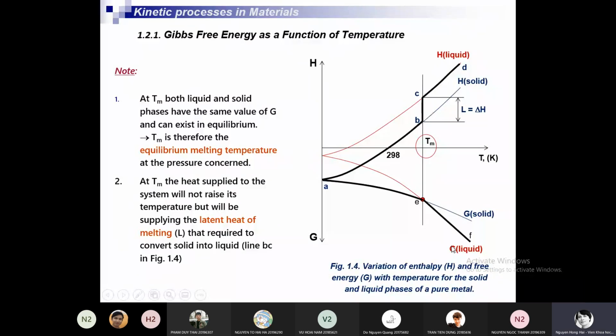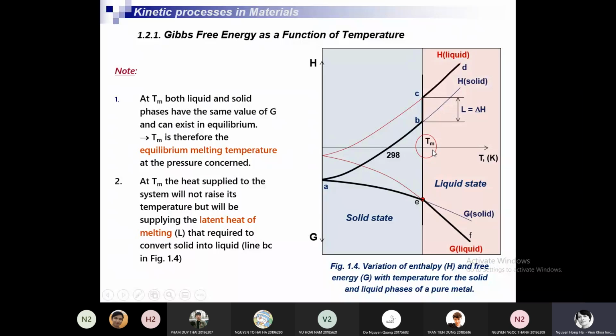See the two curves, the free energy curve and the enthalpy curve. Enthalpy is also energy. And here we have the solid, and higher than this temperature we have the liquid state. We should pay attention to this equilibrium melting temperature, a very important feature of the system. You can see the free energy is a function of temperature, and it decreases with temperature. The higher the temperature, the lower the free energy.